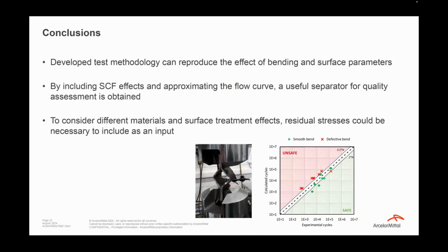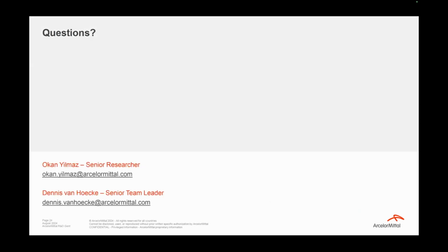And what I see is that the residual stresses would be necessary to include as an input, because with different materials, you will have different limits. You'll have different reactions to the forming, and especially the calculations at high fatigue lives could really benefit from the inclusion of residual stresses. So if there are any questions, I would be really happy to take them.